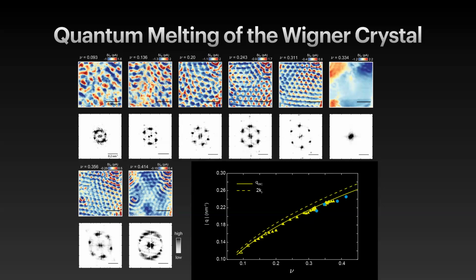So I thought this was a mystery, but then I was talking to Bertrand Halperin and he said that's the only thing that's not a mystery. Because if you go back to these old papers that computed the structure factor for the fractional Hall effect, they will tell you that it has a Q dependent signal, the first feature of which is near the Q of the Wigner crystal. So a Wigner crystal and a fractional Hall effect are not that different in terms of the structure factor, except one, of course, is ordered and at Q equals 0 it has a minimum.